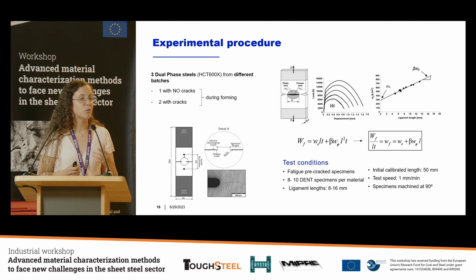propagation. Okay, to do this test, we need samples of the geometry shown in the presentation, which are double-edged notch tension specimens, which have 2 symmetrical cracks, and then these specimens are tested in a tensile test. The particularity of these specimens is that they have to present very sharp notches. And here we perform the test with fatigue pre-cracked notches. Then we obtain these load displacement curves, where we can calculate the area of this curve, which is the work of fracture.